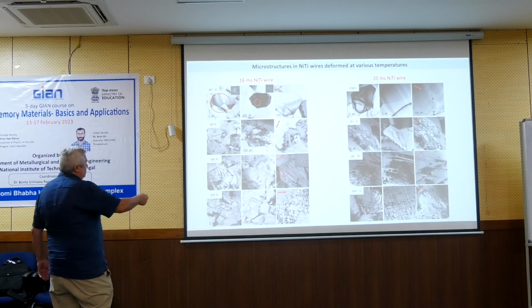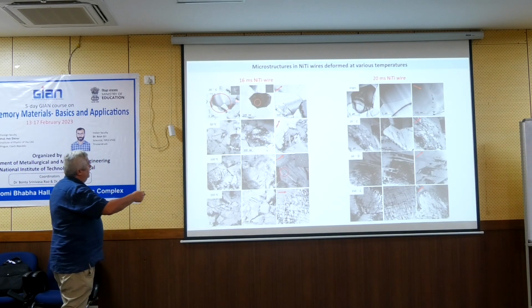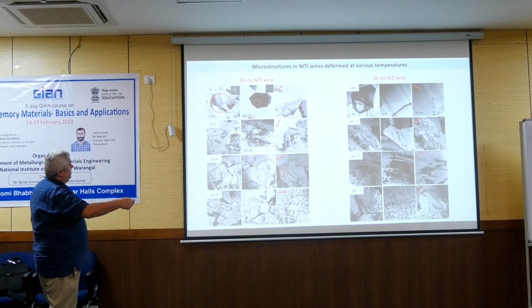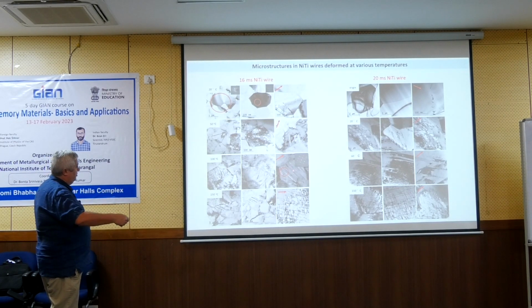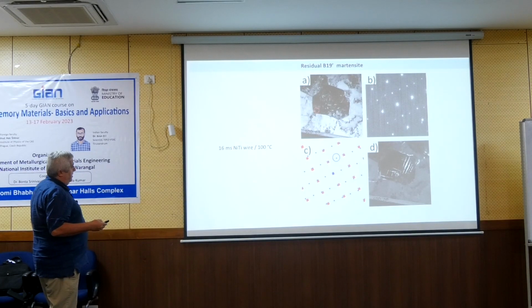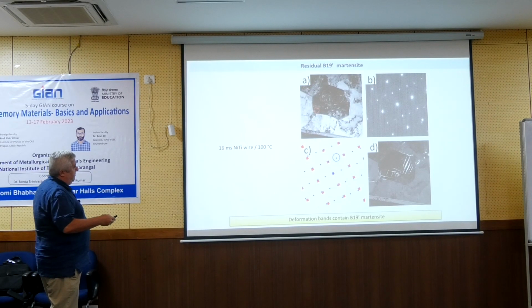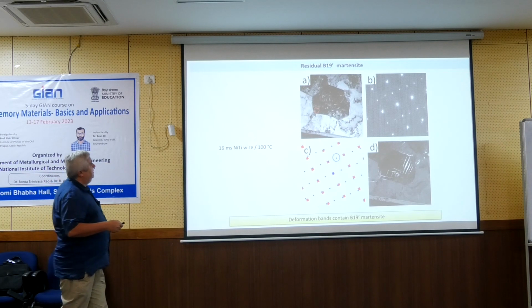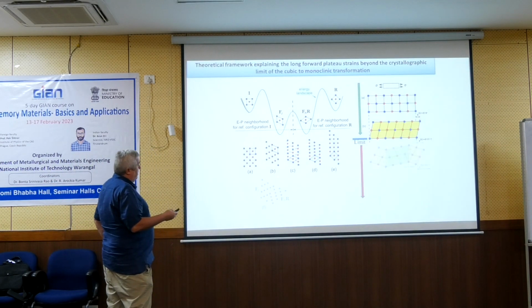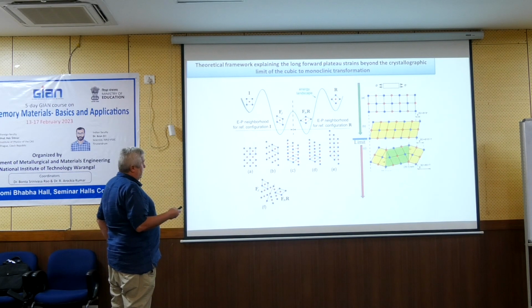Now, this becomes important. If we cycle the wire at room temperature, there are only small dislocation loops here and there, but nothing significant. Around room temperature, deformation bands; at 100 Celsius, lots of bands. At very high temperature, mainly dislocations. This is the evidence for residual martensite. In some bands we can identify the residual martensite in the wire at 100 Celsius, but it's not so important.